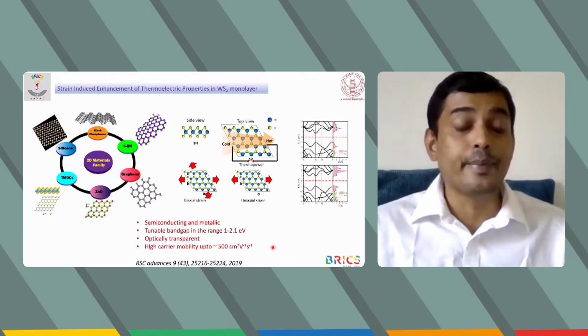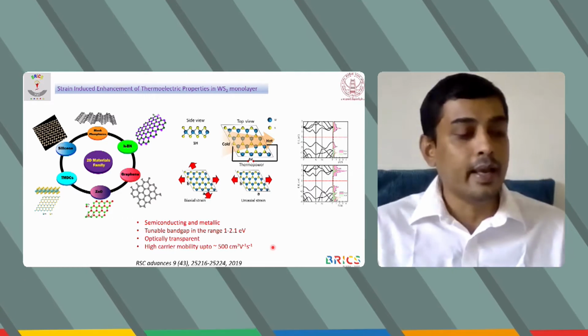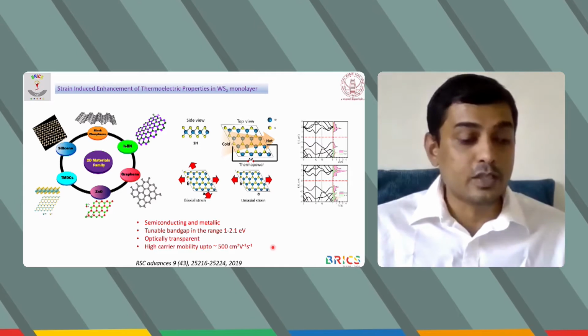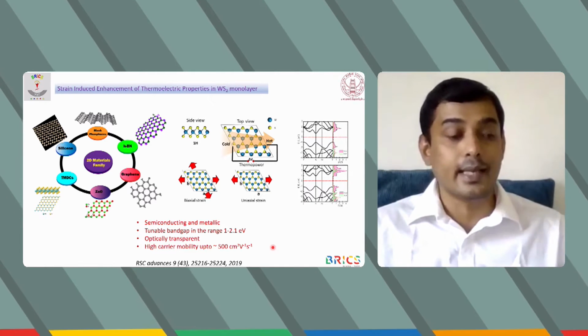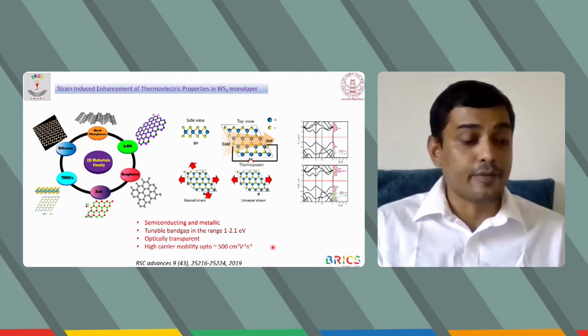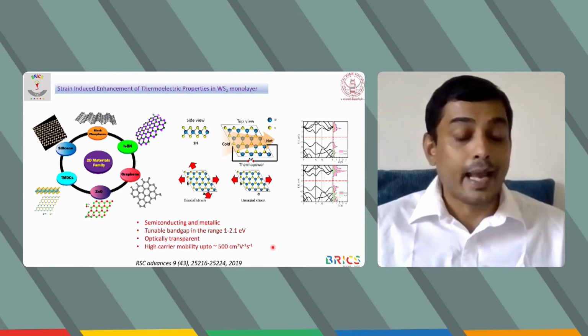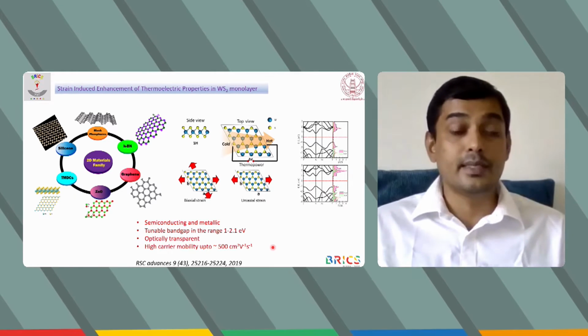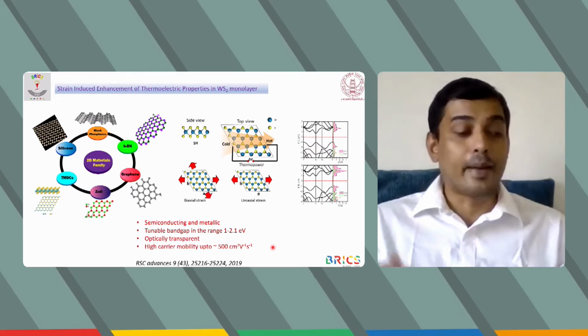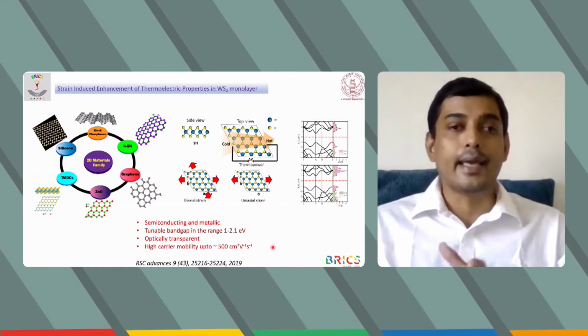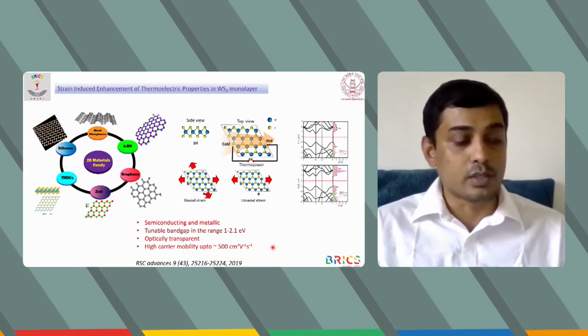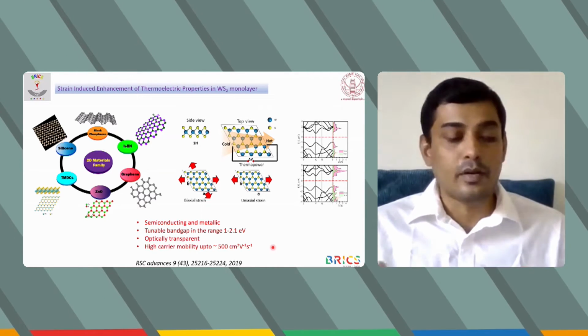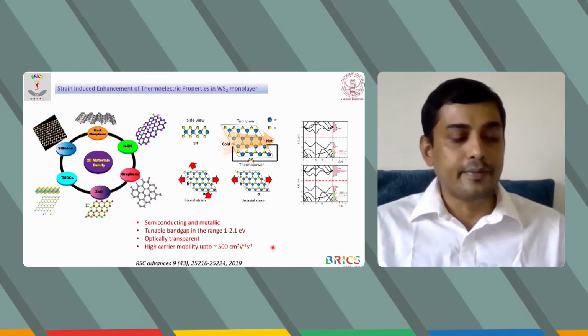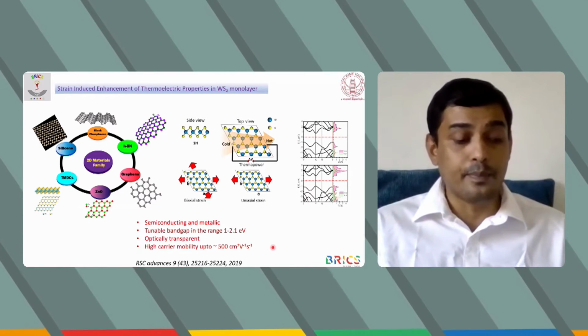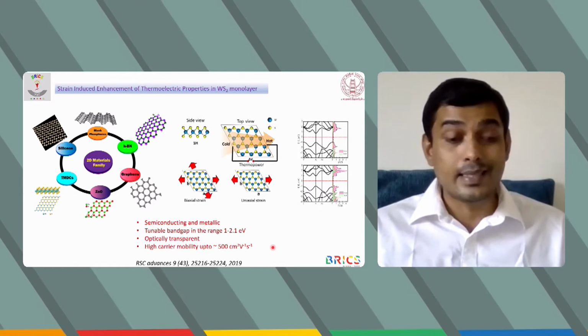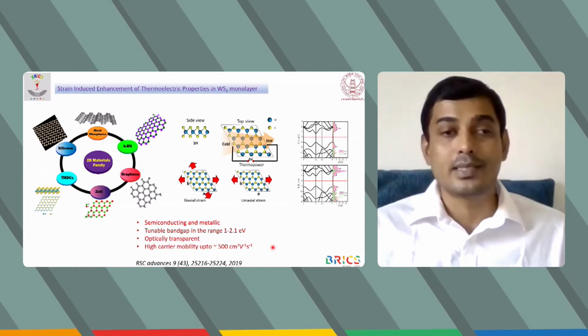Now, many presenters, including my previous presenter, Yuri, have presented the important properties of TMDCs, which are much better than graphene. And unlike graphene, we can tune the band gap of the materials. Hence, we also use one such TMDC called WS2, which has a direct band gap for the monolayer and becomes indirect when you use multiple layers of WS2. Now, we studied the thermoelectric behavior of WS2 theoretically by using DFT, and we found that the thermoelectric behavior of the material changes when we are applying stress or strain to the WS2.